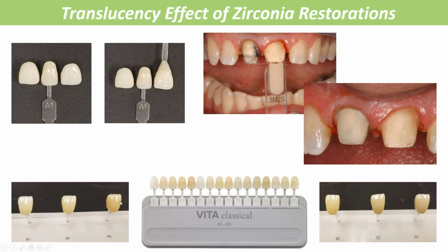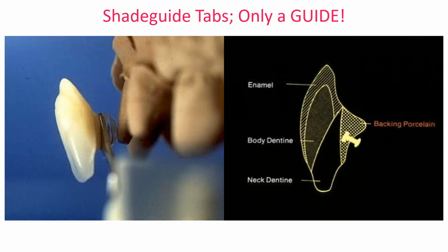So at the end of the day, if you are looking at zirconia, after you sinter it and after you have a preparation color background, you should achieve the shades that match the shade guide or shade tabs individually that VITA produces if you're getting VITA materials. Of course, this really only conforms to VITA shade, VITA materials. We've done a lengthy study, took us a long time to come out with an ST, which is super translucent, or an XT, which is an extra translucent zirconia that comes out and is aligned with each shade tab that we produce. So this is achievable, and you can get some really good results.